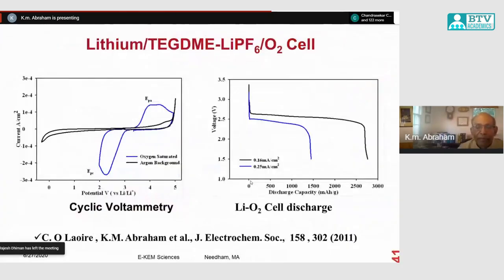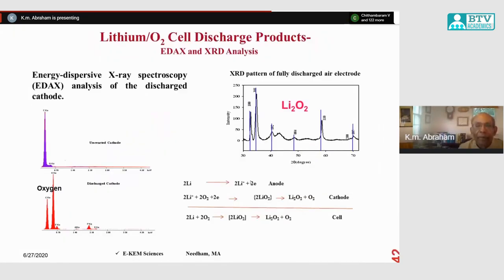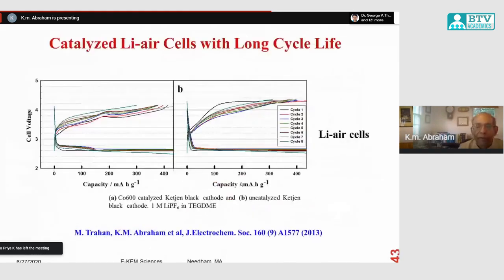So we did a lot of electrochemistry, battery discharge, and looked at the discharge products through analytical chemistry using energy dispersive X-ray spectroscopy and X-ray diffraction patterns, and chemical analysis showed that the reaction is this. When you discharge your battery, you reduce your oxygen to lithium peroxide, and you can charge the battery as well. You can charge and discharge it if you use a catalyst.